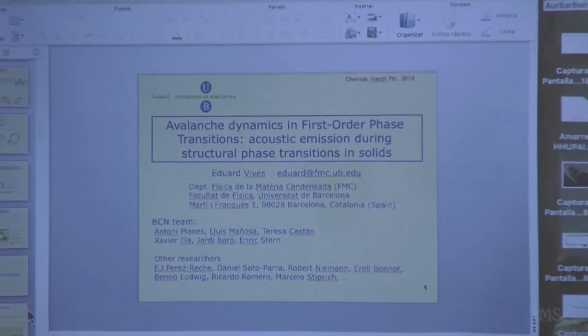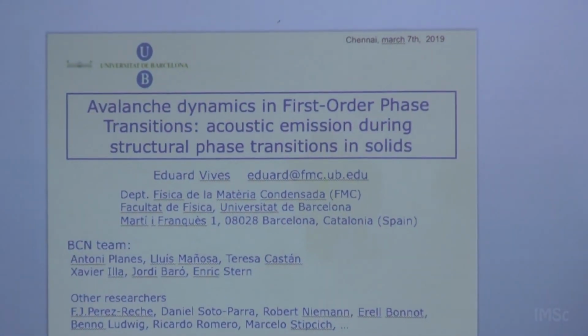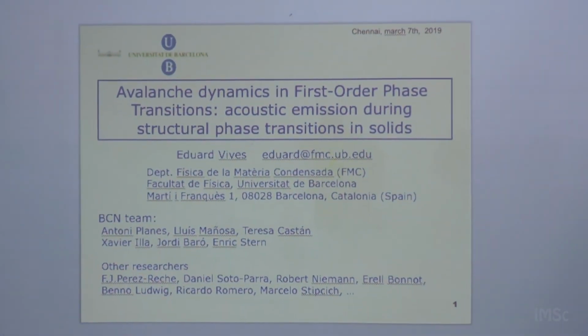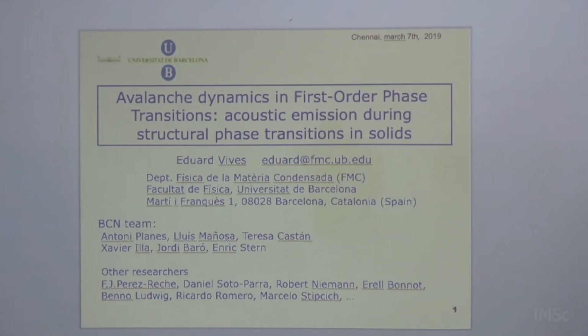Other question, this is what you measure after many loops, so in steady state. Otherwise, the exponent changes with time. Yeah, I jumped too fast on this, but yeah. In fact, what happens is that when you have not cycled, the distribution is not a power law. It has an exponential correction. Let me show. What is it?